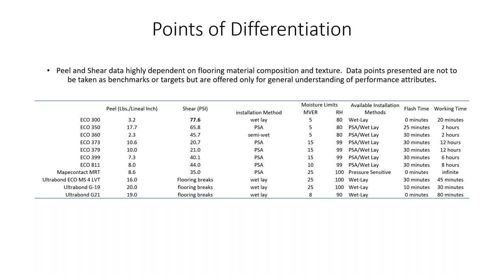399, our product that we promote as gap controlling, again, it's got great peel, a little bit less than some of the other super sticky ones, which kind of makes sense. The tougher you are, the more brittle you can get, so that number changes. But the shear values get to be much higher. 811, same thing. MRT, big numbers as well, more than adequate peel strength and shear strength. But when we look at those reactive systems, 16 pounds of peel for MS 4 LVT, G19, G21, all big numbers. And then the shear values, they simply just don't move. The flooring will break before you do. But again, it's a wet lay installation method. Moisture values are much higher, with a limited amount of working time.